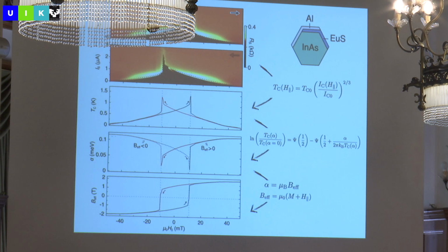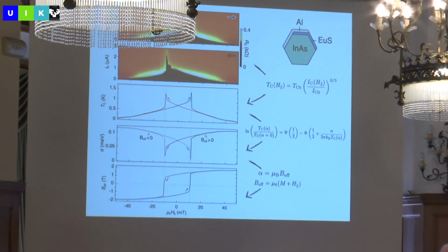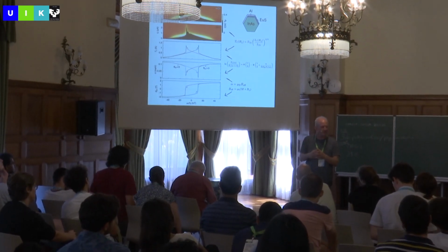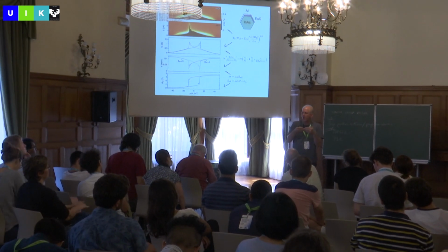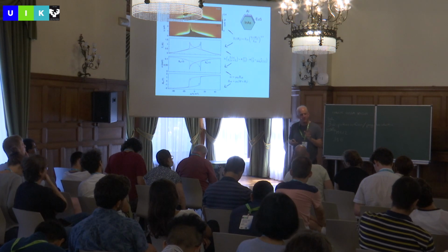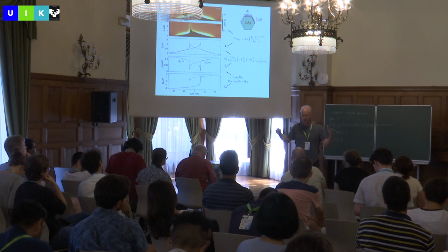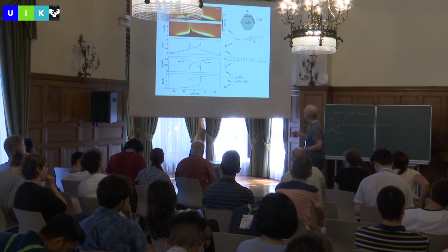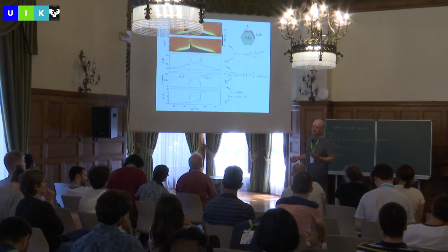Now, a new physics problem, and I will tell you for you theorists who are here to jot down new physics problems. When I say the average magnetic field is zero at this point, what do I mean average? Well, what I mean by average, because it's a ferromagnet, there are domains, and I'm just demagnetizing the domains. If the domains are small compared to the coherence length, then the superconductor just sees a bunch of averaged domains. And that's what you could say by averaging. If, on the other hand, the domains were large compared to the coherence length, that's a different limit. In that limit, superconductivity only exists at the domain walls, and it has to percolate through the system. So it's a very interesting question if you have a ferromagnet with domains and a superconductor with a coherence length. What does it mean to have this spike as the average goes through zero? Average over what? Open problem.